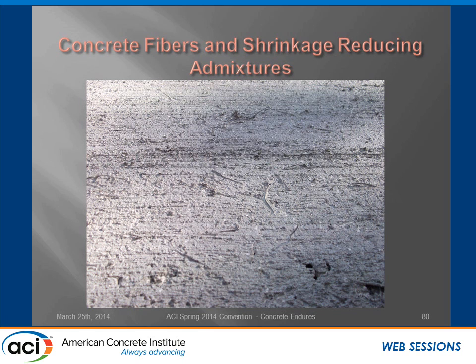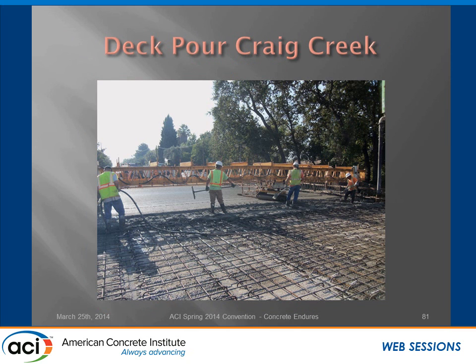One was to attain a quiet deck spec with our groove and grind spec, and the other was we wanted to get the curing compound off about 2 months later so we could inspect the deck to see if we had any cracks. And since I'm standing up here, you can probably imagine we didn't get any cracks, but that's a couple slides from here.